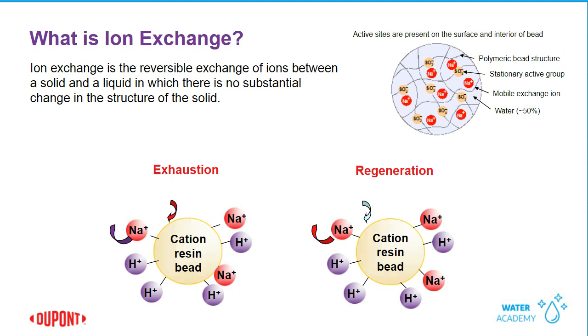Now, another thing I wanted to point out here about the polymeric resin beads, if you look up in the right-hand corner of your screen, you'll see a little diagram. So I already mentioned the polymeric bead structure, but there's stationary active groups that are permanently attached to these polymeric chains that run throughout the bead and on the bead surface. And these mobile counterions interact with these stationary active groups. So hydrogen and sodium in this example. Another thing I wanted to point out is that the resin bead actually contains about 50% water, and that's necessary for the transport of these ions to get from active site to active site and into and out of the bead.